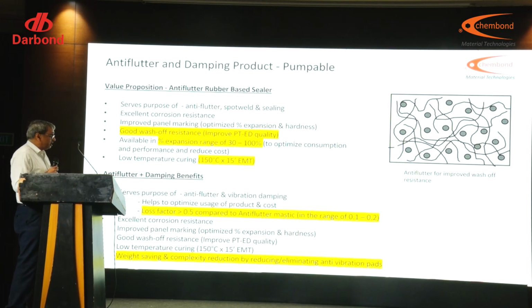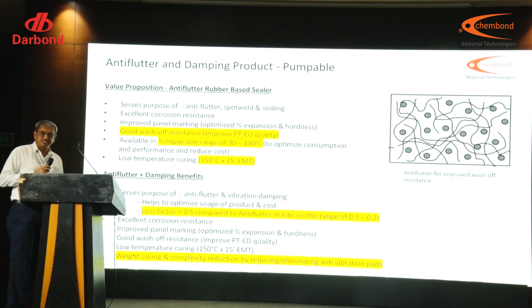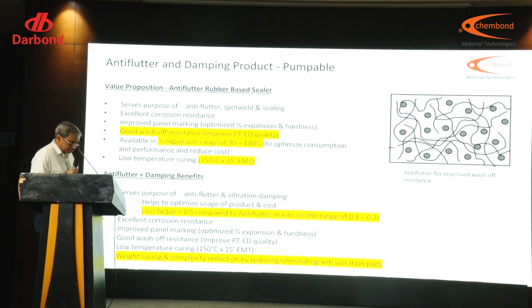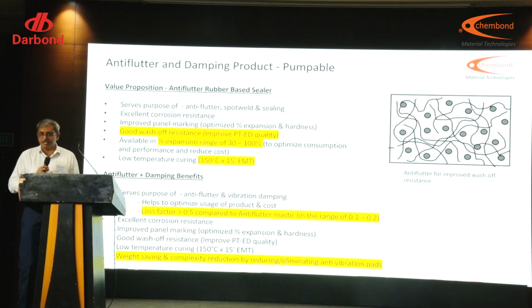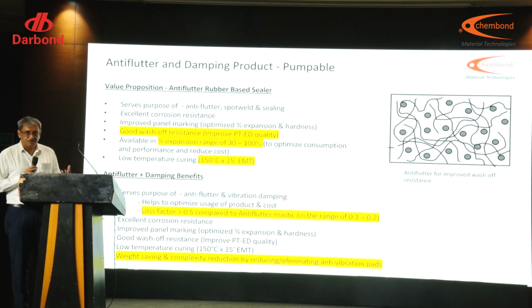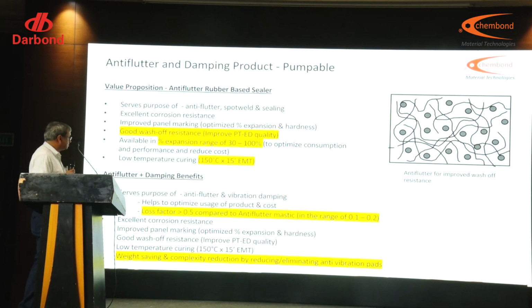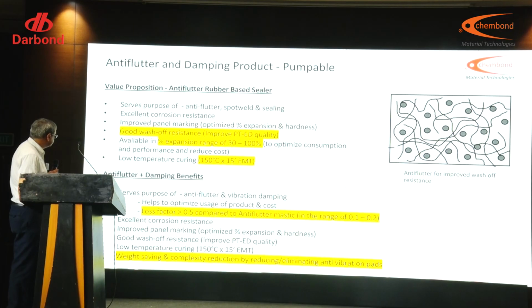Another one is a rubber-based anti-flutter as well as high damping foam. The previous one you saw is in preformed shape; this one is in pumpable form. With pumpable products, there is an issue when the body passes through the PT-ED process: a lot of PT contamination due to wash-off of the pumpable sealer. We provide a technology based on fibers, which in paste form provide very good wet cohesive strength, and the product retains its shape even in pumpable paste form. It improves the paint quality and reduces sludge formation.